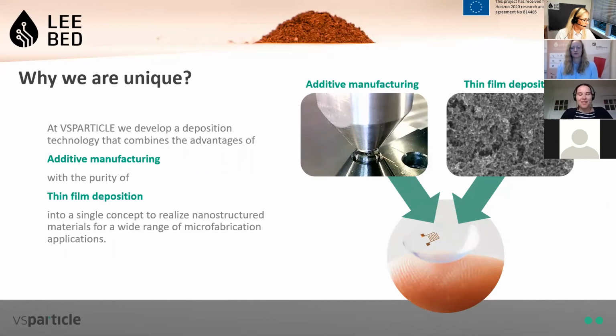Why? Because we combine the advantage of additive manufacturing with the purity of thin film deposition. And so the technology allows you to locally deposit the material onto your substrate, and this removes the need for masking or etching, which is required in other thin film deposition methods like sputtering. And on the other side, the deposited thin film is very pure. It's free of solvents, and we don't need a suspension or an adhesive like other additive methods like inkjet need.